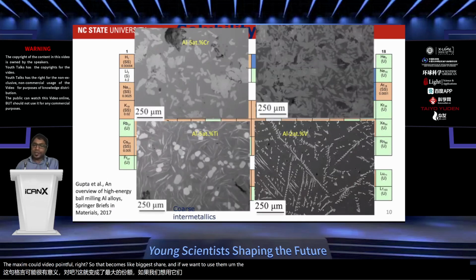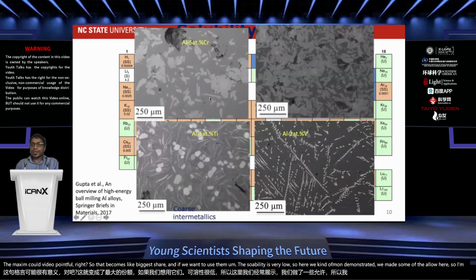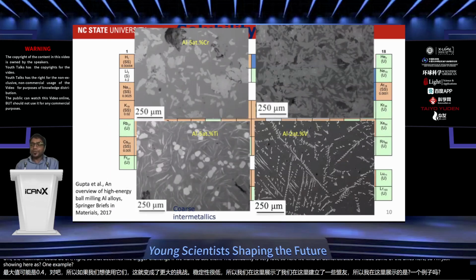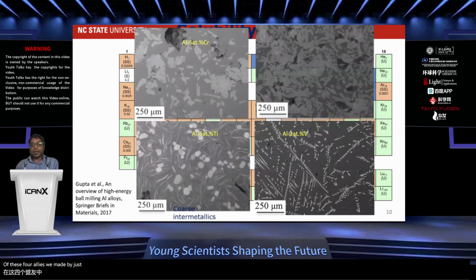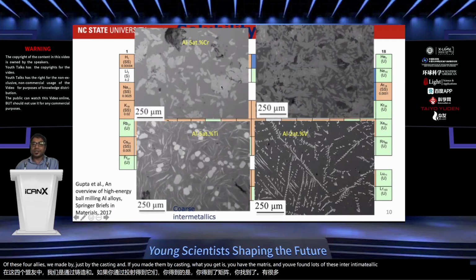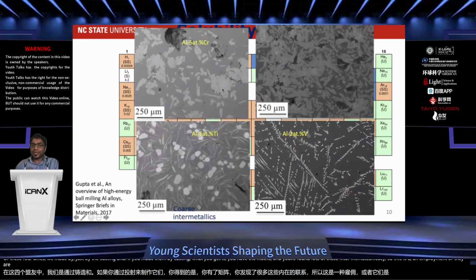The solubility is very low. So here we demonstrated, we made some of the alloys. I'm just showing one example of these 4 alloys we made by casting. If you make them by casting, you have the matrix and you form lots of these intermetallics. This is the aluminum chromium. So these are aluminum chromium intermetallics.